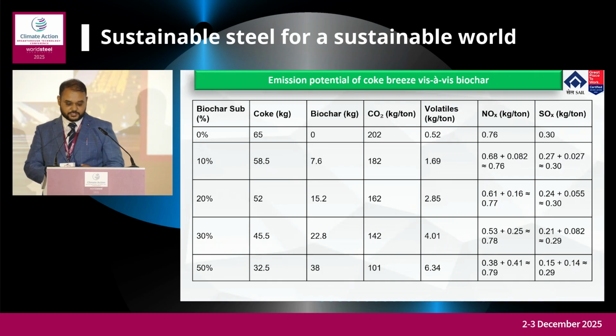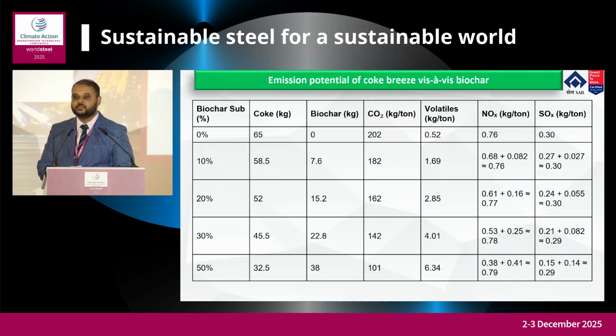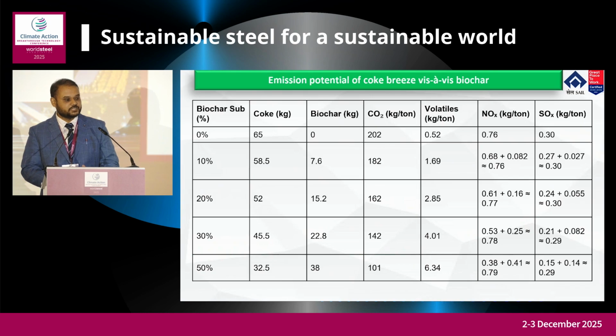Now, this is the theoretical emission potential of different biochar substitution vis-a-vis original coke breeze. There was a large concern for us as well as for steel makers that biochar has a higher VM. Definitely it is a higher VM, while coke breeze has a VM of around 0.8 to 1%, whereas the biochar we have chosen has 7 to 8%, not max 10%, which can be a very good potential challenge.